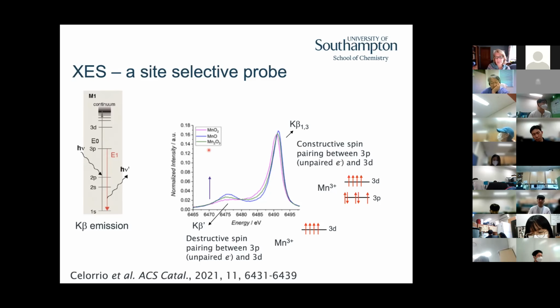And this is by using X-ray emission spectroscopy. So normally what we do is we do the fluorescence and we collect all of the fluorescence photons from all of the different possible fluorescence paths. So this is just showing the K beta emission, but we normally collect the K beta and the K alpha emission. So we collect a wider range of the fluorescence signal to try to get the best data. But if we use a second monochromator to ensure that we're only collecting the emission from this pathway, then we can get greater sensitivity, so that we then collect the emission spectra. So we're now looking at the K beta emission spectra.